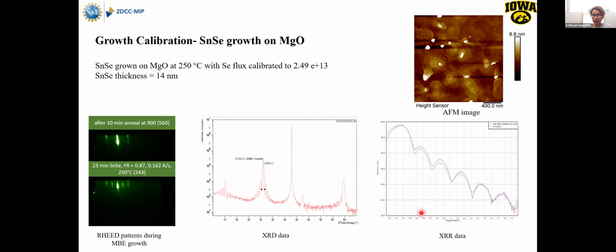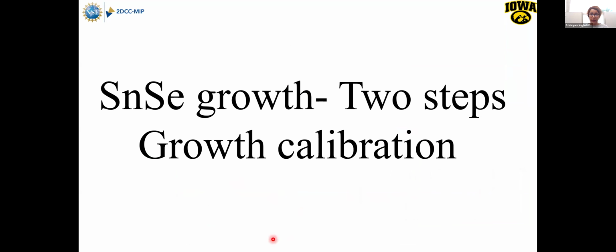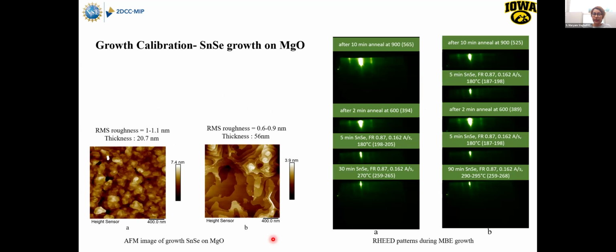And here you can see the XRR data that confirm the thickness, and also XRD, very sharp, nice tin selenide peaks, and also RHEED patterns confirm that. The other thing we tried is growing the tin selenide with two steps to improve the film quality. And here we play with the annealing time and also the temperature. And you can see the film quality gets a lot better.